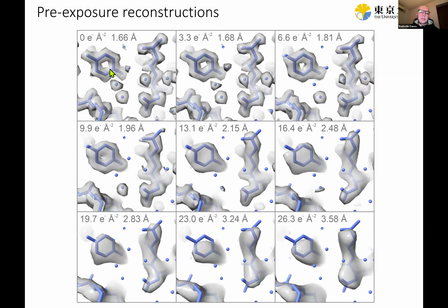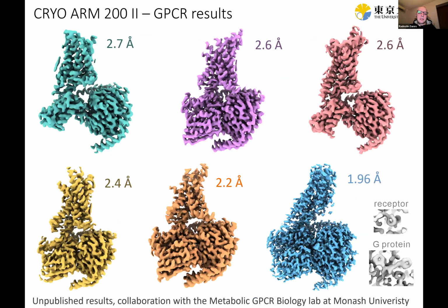These are examples of map features at the different pre-exposure levels. So we see, of course, degradation in the overall fidelity of the map. And what was surprising to me, at least, is that even after about 20 electrons per square angstrom of pre-exposure, the map still reached below 3 angstrom. Of course, the water densities are completely gone by then. These are the water molecules here. And you see by that time they are completely gone, but still under 3 angstrom after 20 electrons per square angstrom was a bit surprising.